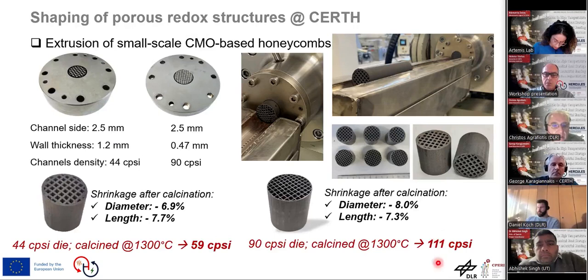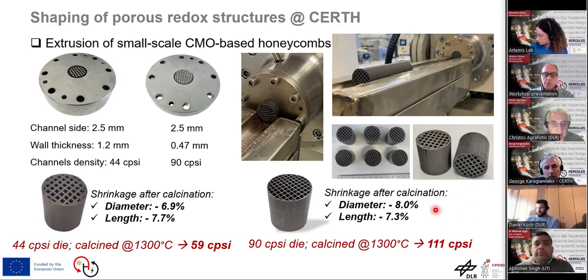The next slide shows these kinds of honeycombs that are produced in CERTH by extrusion, as you can see here, 2 different CPSI. CPSI is channels per square inch. It's essentially, as you can see in the photographs, how many channels available for gas flow its porous structure has. And you see how these objects come out of an extruder, this stiff dough that comes out of the die that defines the channels, and then it's dried and then shaped and sintered to become a rigid cylinder, as you can see there.